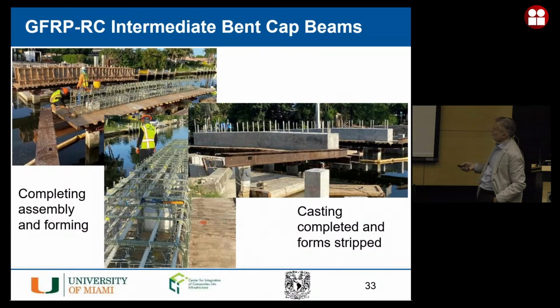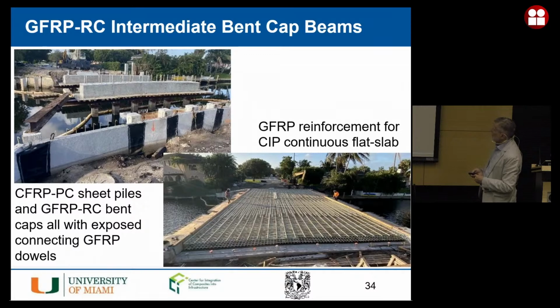Okay, so this again, the completing of the assembling of the form is the same thing. The casting, nothing special. Here you see the CFRP sheet piles that are driven as conventional piles, but you look at this, the connection to the cap is with GFRP L shapes. You see this is lighter in color. So there is a combination of reinforcement. And in the case of piles, now the Florida DOT allows you to use carbon FRP tendons and GFRP stirrups or ties. Okay, this sea of bars is just the deck, as you can see, 2 layers, so continuous flat slab.